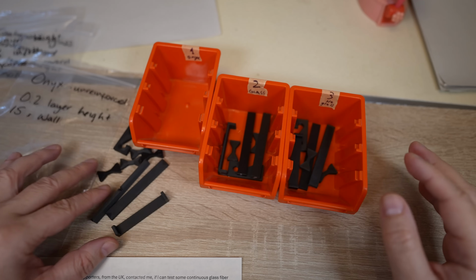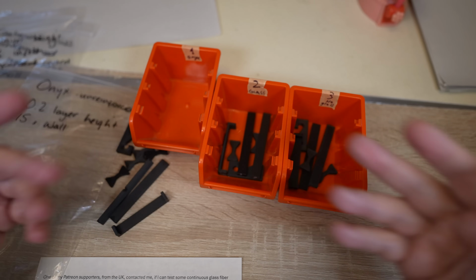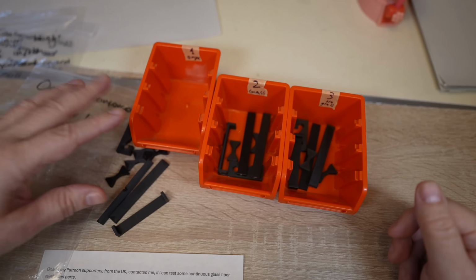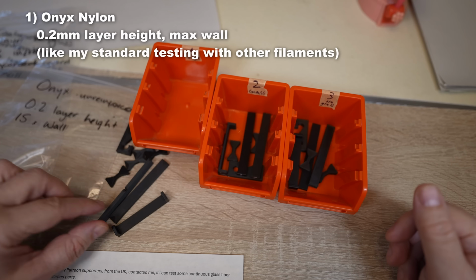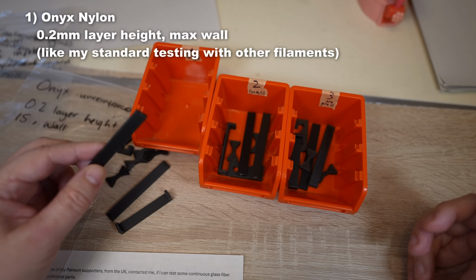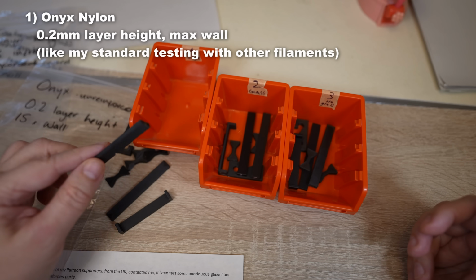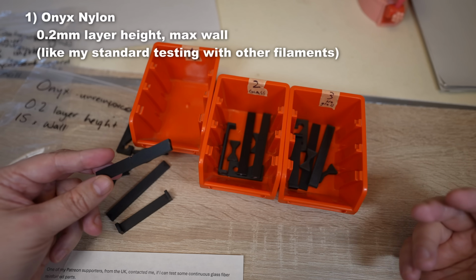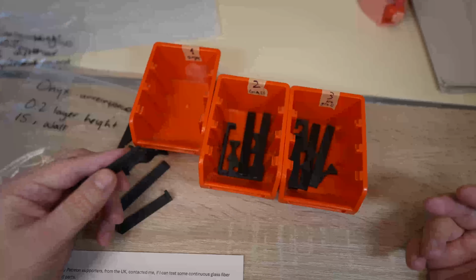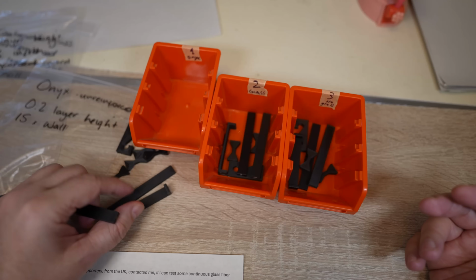I have three groups of test objects. They are in these bags, only I moved them here because it's easier to operate with them. The first group is just a set of carbon fiber nylon Onyx test pieces with 0.2 mm layer height and the maximum number of walls. These are just typical carbon fiber reinforced filaments with small fibers, like other filaments I tested so far. And this group is printed with settings which I usually use for my test objects.